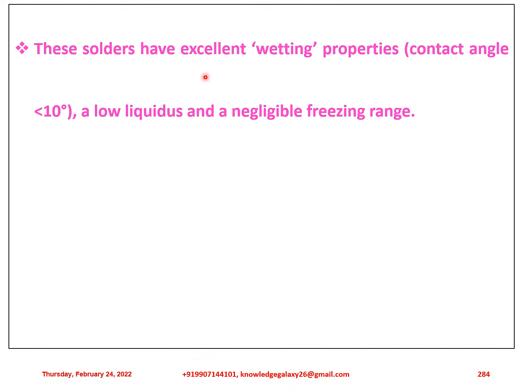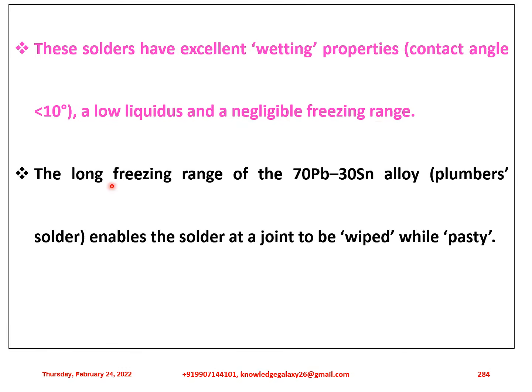These solders have excellent wetting properties, which have a contact angle of less than 10 degrees, a low liquidus and a negligible freezing range. The long freezing range of the 70 Pb and 30 Sn alloy, that is called plumber's solder, enables the solder at a joint to be wiped while pasty.